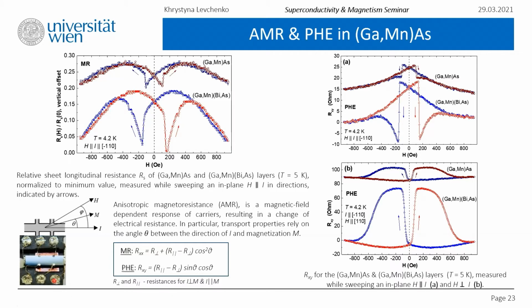Beforehand, samples are pre-magnetized to negative values, to -1 kilo-Oersted. And then we proceed to measure with the magnetic field being swept from plus to minus value, from plus 950 to minus 950 Oersted. The direction of sweep is shown by the arrows. So we start here from 0, go to the plus side of the field, come to some point, the recurrence point, where the negative slope is observed, and then coming back, coming to the same starting point in the 0 field, and symmetric hysteresis on the other side of the field.